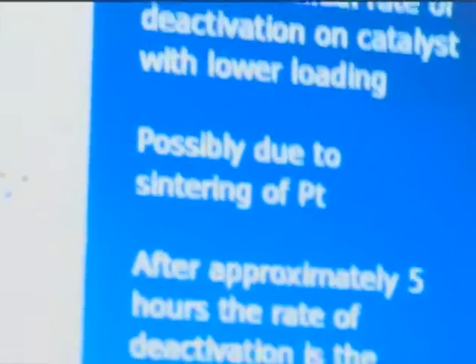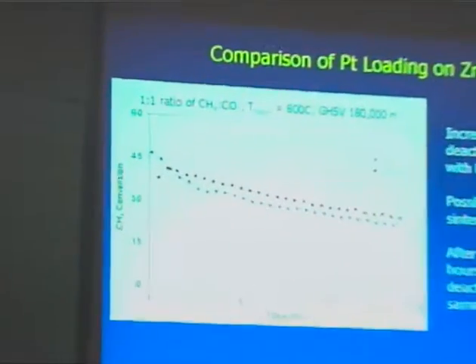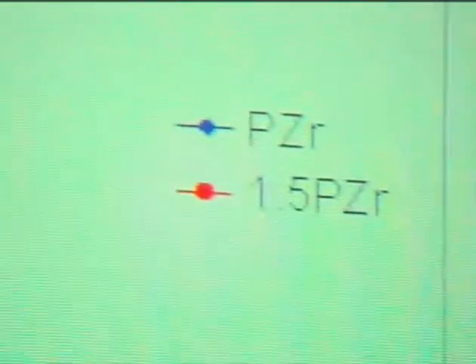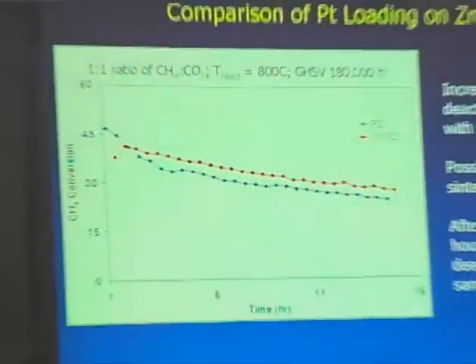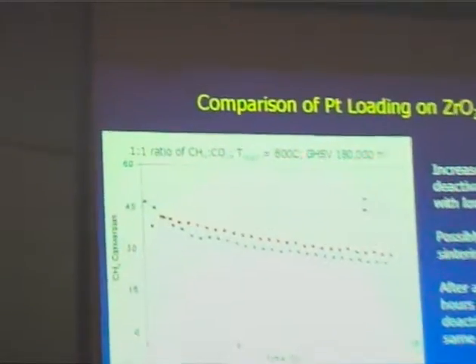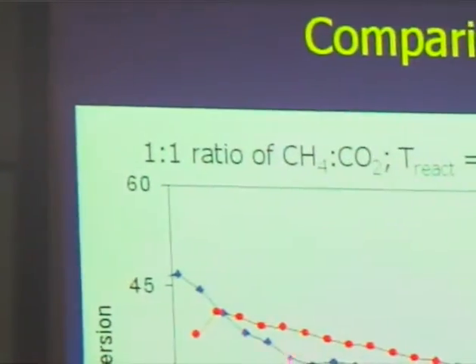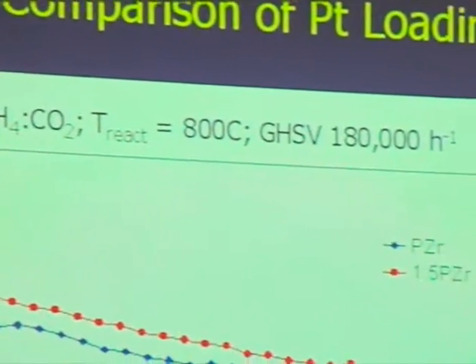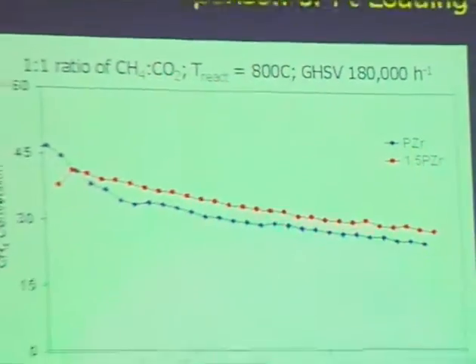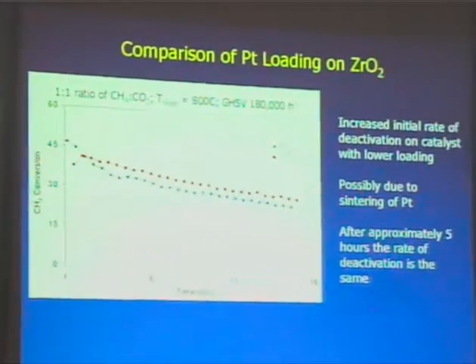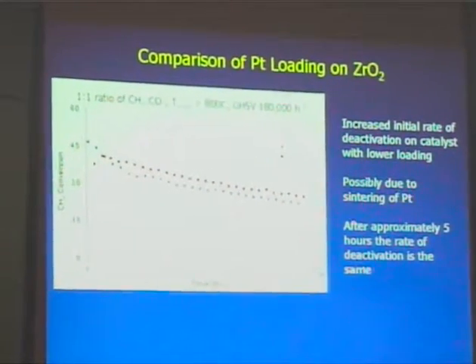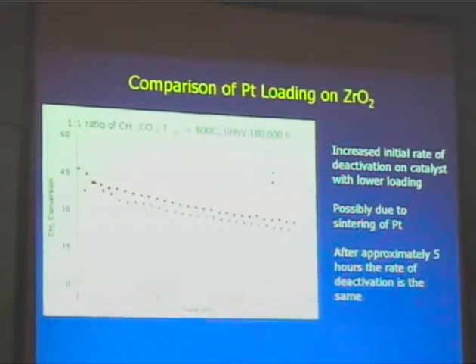If we look at the comparison of the platinum loading, and this compares the blue, which is the 0.5 weight percent, as opposed to the 1.5 weight percent, we see an initial increase in the rate of deactivation on the catalyst with the lower loading. And this was somewhat of a surprise to us because we thought with the catalyst with the lower loading we have a higher interfacial area, so we should have less carbon deposition, less deactivation. What we think is happening here is that we are having sintering of the metal occurring, because after about 5 hours on stream, the rate of deactivation for both materials is very similar. And so after that initial rate of sintering occurs, you have similar materials and similar rates of deactivation.